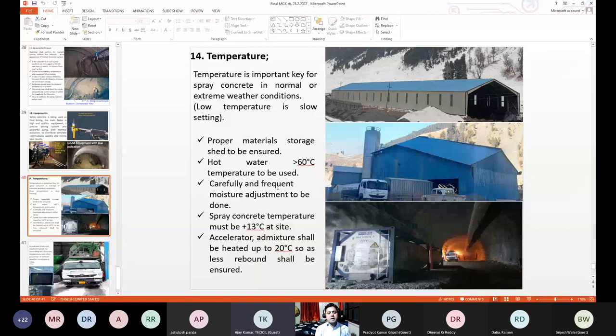At our extreme conditions, we always follow the best practices to keep the material in dry condition, and if your material, your procedure is good, then you can achieve good results. You can see on the screen, the accelerator is being kept inside the tunnel, your material will be heated properly, will be free from the snow or the low temperature, and it will work always nicely.